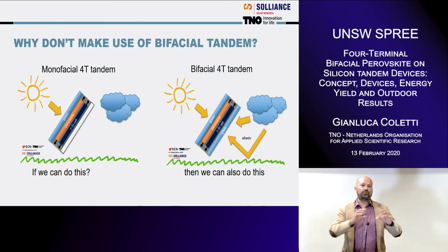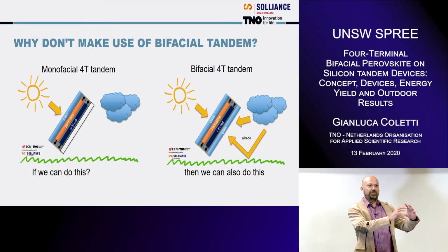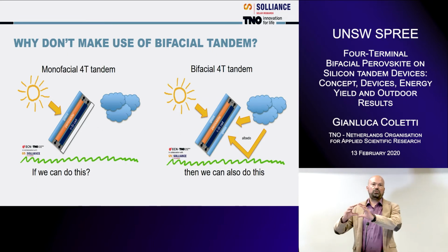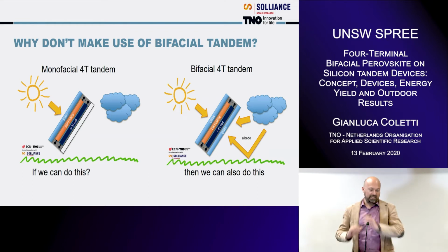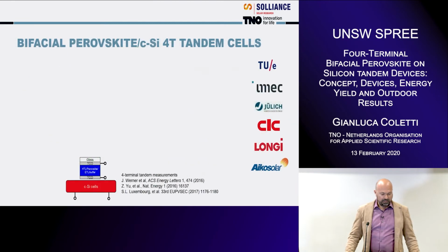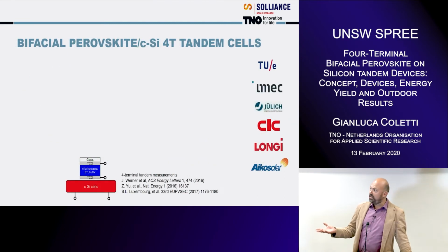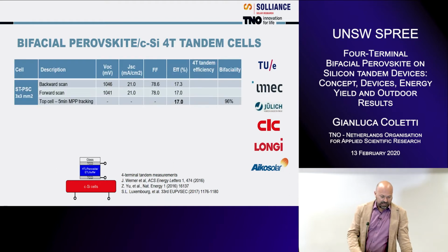So you go from a single junction, normally monofacial. We already see there is a lot of bifacial single junction, and you add another device, but you keep this feature of the rear side, and we will see later why. So those are results. We essentially put together perovskite with silicon. This is a four-terminal device. And our colleagues at Solliance did this excellent job. They were able to make